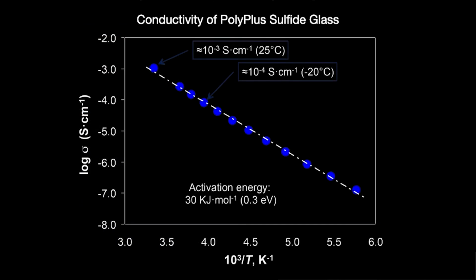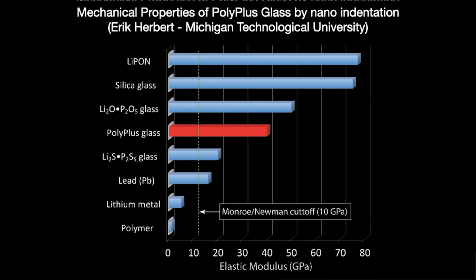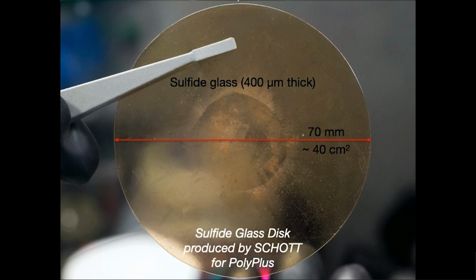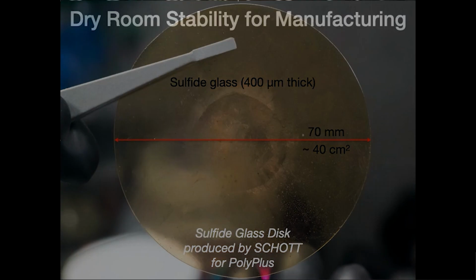The conductivity of sulfide glasses is, as I mentioned, very high. You can see here, even at minus 20 C, the conductivity is at 10 to the minus 4 Siemens per centimeter. And these materials are sufficiently hard, as I mentioned, to stop dendrites. In fact, the elastic modulus of this glass approaches that of oxide glasses. So these are strong glasses. Here you see about a 70 millimeter disc of glass that was produced for us by Schott. It's about 400 microns thick.